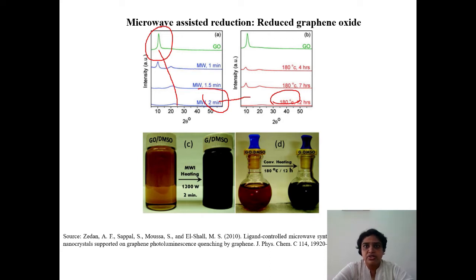So this is very interesting to know that conventional processing took 7 hours to get the reduced oxide. This is just the inherent feature of the sample. So here it's seen, this is your graphene oxide dissolved in DMSO and then processed for 2 minutes in microwave at 1200 watt. And this we can do in our domestic oven as well. So very simple setup and very less power consumption. However, in the conventional method, it took 12 hours at 180 degrees centigrade. Such a huge difference in time as well as power.